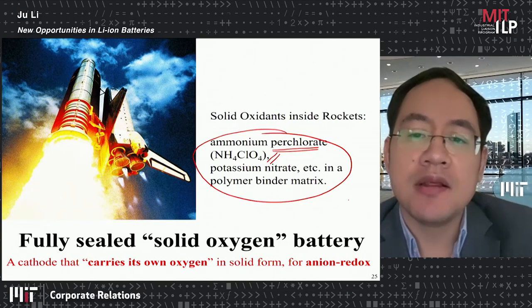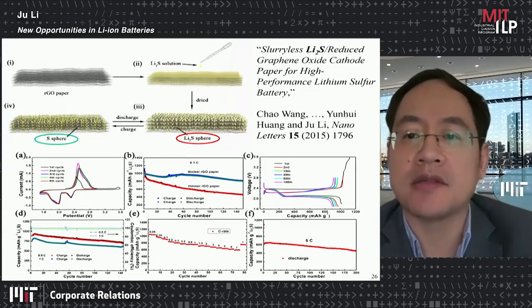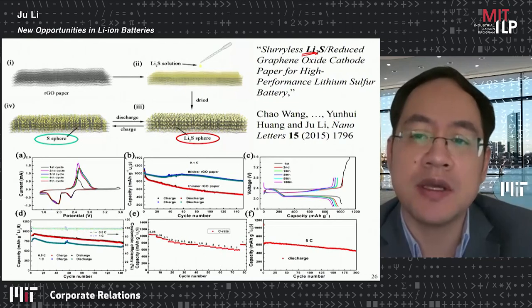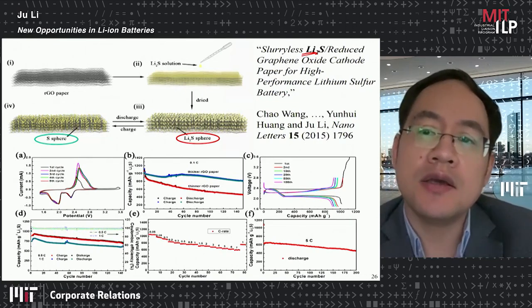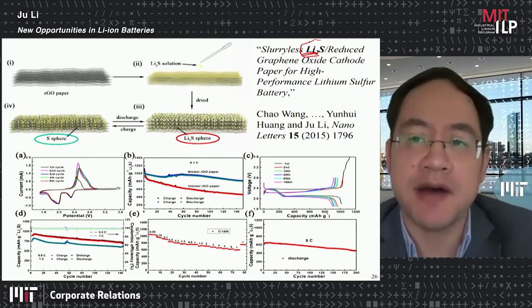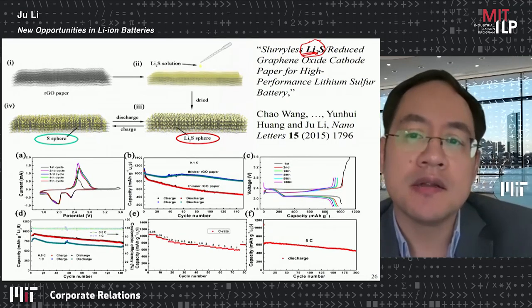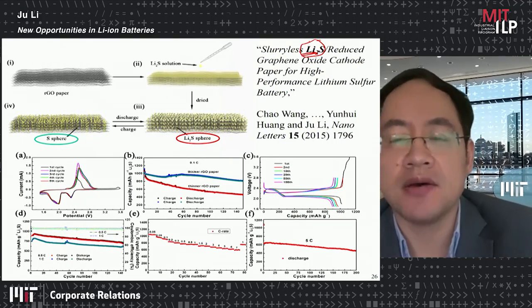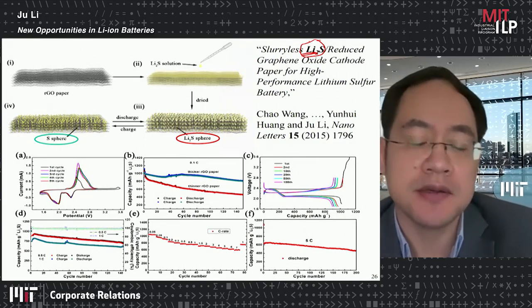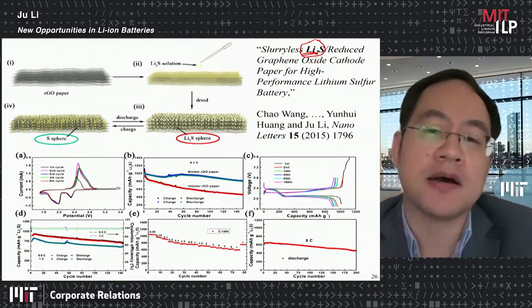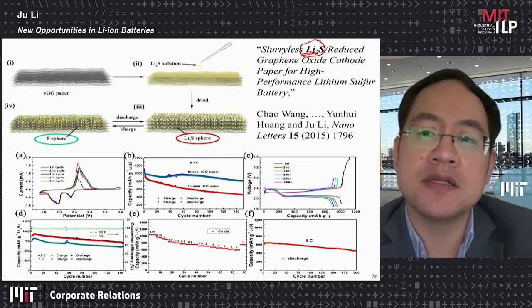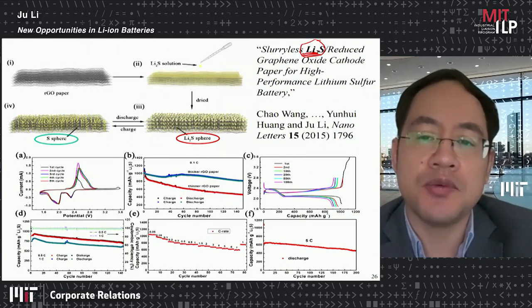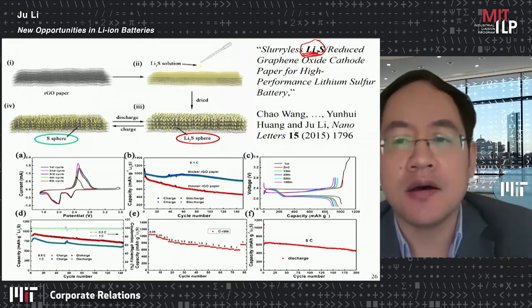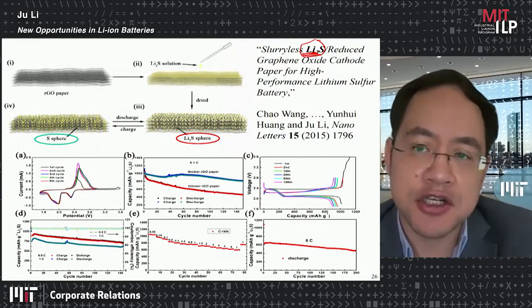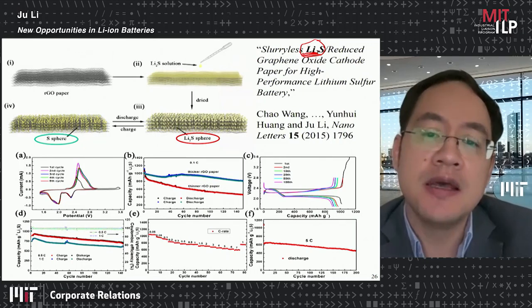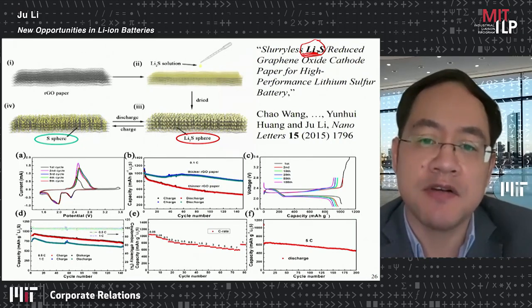And it turns out that in sulfur, you can definitely do that. So we've written a paper with Professor Yunhui Huang starting with this lithium sulfide. So in this case, the anode doesn't have to be lithium metal. It can be graphite or silicon. And in that case, we can have this system which starts out with a lithiated system and we always charge the system first, unlike the typical lithium sulfur batteries.